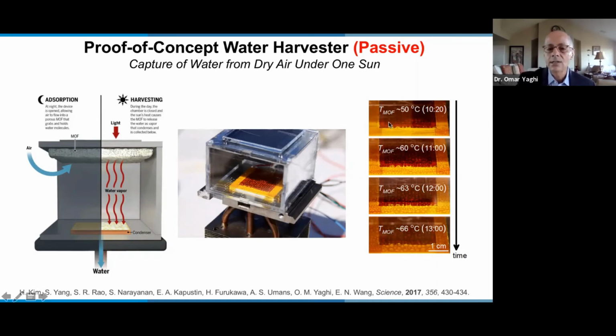You see here that as the box is exposed to sunlight, the inside of the box heats up: 50 degrees C, 60 degrees C, and so on. But as it heats up, the water comes out of the MOF. You can see here droplets that grow larger and larger. And this was very exciting because it means that the MOF can work in real life conditions.